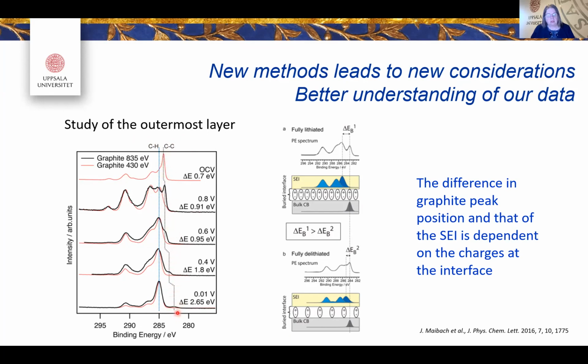And this shift, we were looking at that shift a little bit extra. And we explain this shift as being important, where you have more non-conducting species in the SEI. So you have a certain binding energy difference when you have the intercalated graphite. And this means that you get a lot of dipole moment at the buried interface. And in the previous slide, we explained that as a lot of lithium. And when you deintercalate your lithium, you actually remove a lot of that charge. You have a smaller binding energy difference. And this is something you have to think of, especially when you move, like we are doing now, from postmortem studies to more operando studies.